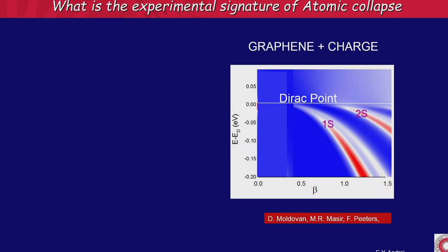So what is the experimental signature of atomic collapse in graphene? This is a simulation by my collaborators here. This is the energy as a function of beta. When beta is less than a half, you have unbound states, just Klein tunneling. And as beta is above a half, you're going to start having these collapse states. And this looks like an artificial atom, but this is not quite because the sequence is not a Rydberg series. But the levels start dropping down into the